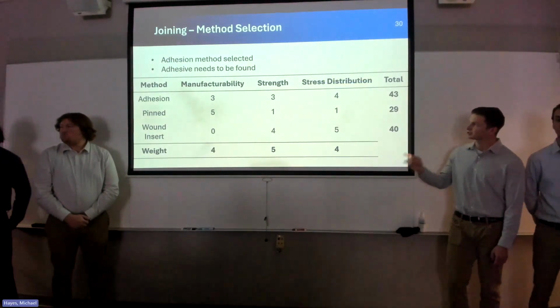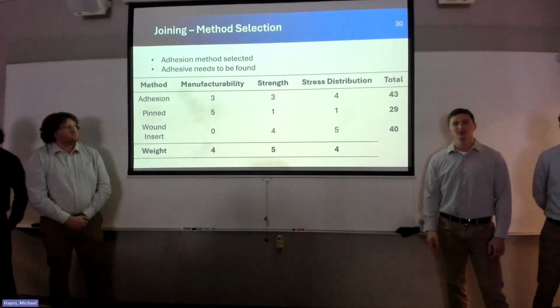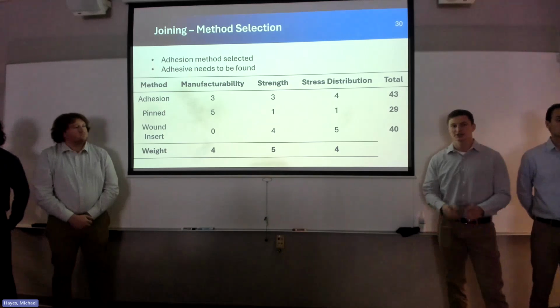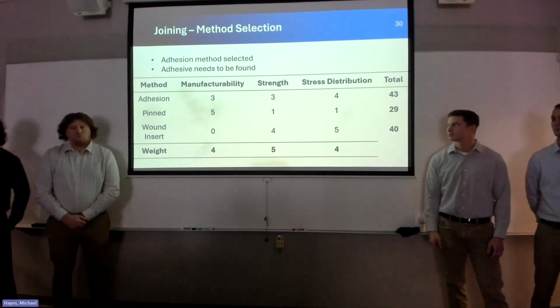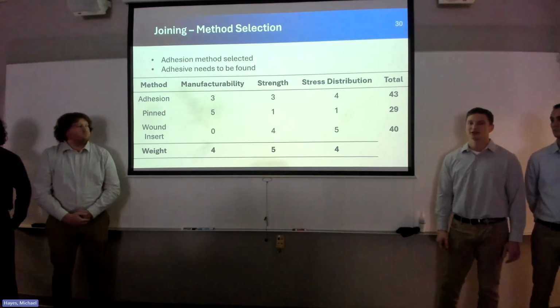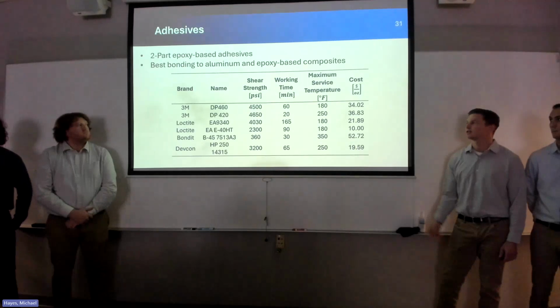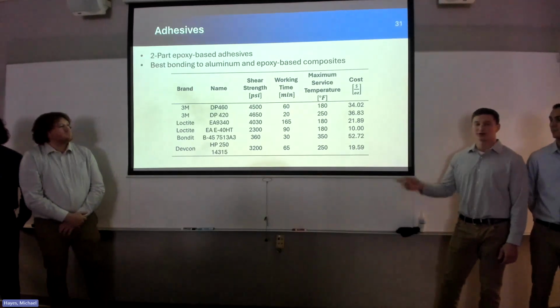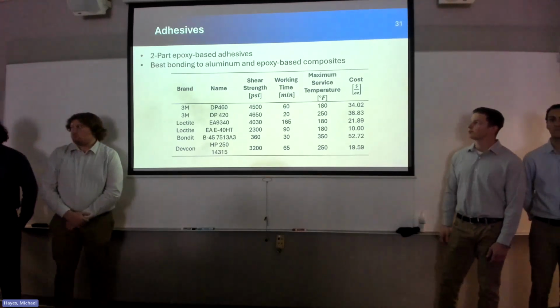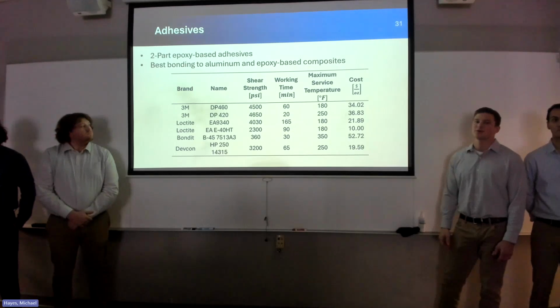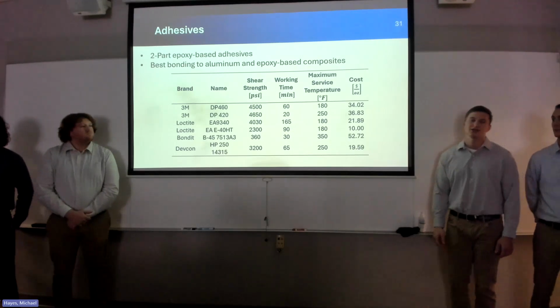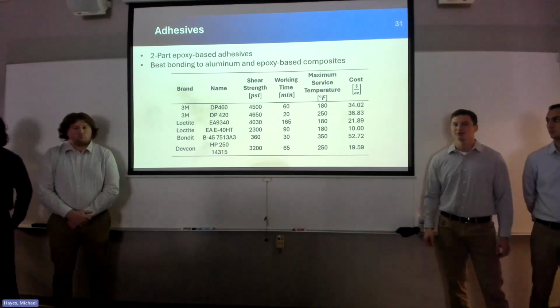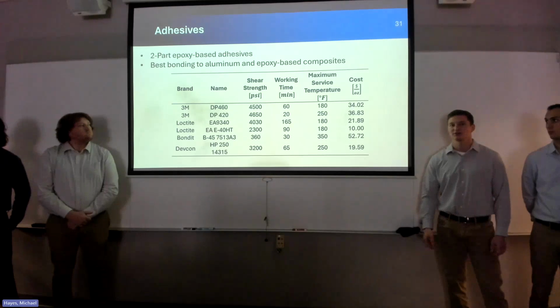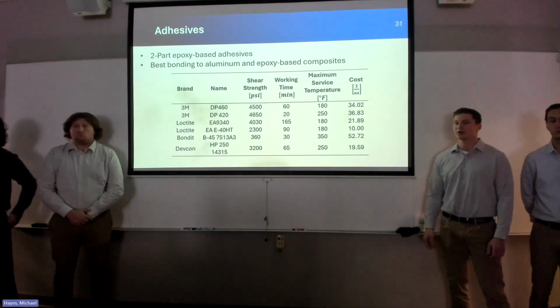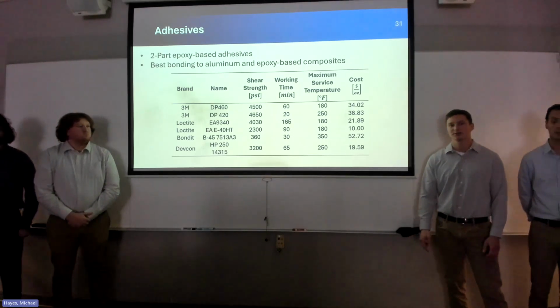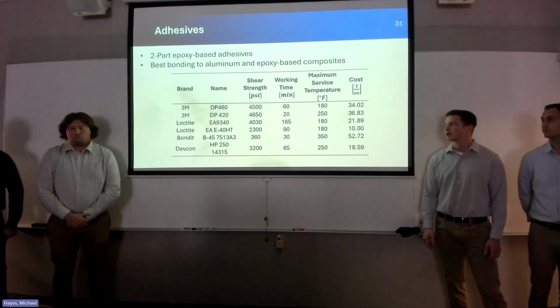Looking at our decision matrix, we ended up going with the adhesion method, as it combines that strength distribution as well as the manufacturability. And this leads us to the fact that we need to pick an adhesive that we'll use to combine the two. For an adhesive, we went with looking into 2-part epoxy-based adhesives. We wanted an epoxy-based adhesive, as the tube itself will be epoxy-based in the matrix. This will provide us with the strongest bond, and we wanted to make sure that the bond between the aluminum and the composite tube is as high as possible.